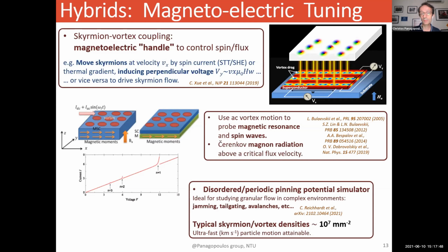Another idea that has been proposed in such a system is a disordered periodic pinning potential simulator, which would be ideal to study granular flow in complex environments, such as jamming, tailgating, avalanches, etc., including in earth science studies. But also one would expect in such a case to have a typical skyrmion-vortex density of up to 10 to the 7 per millimeter squared and induce ultrafast particle motion in the order of kilometers per second.